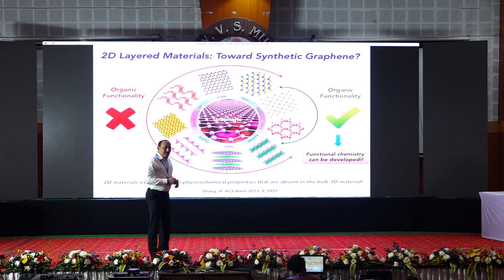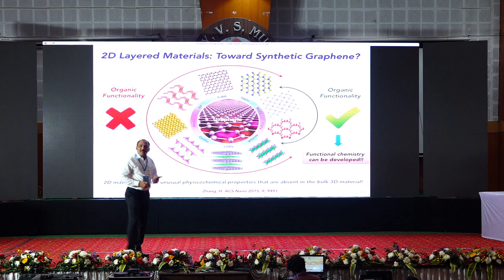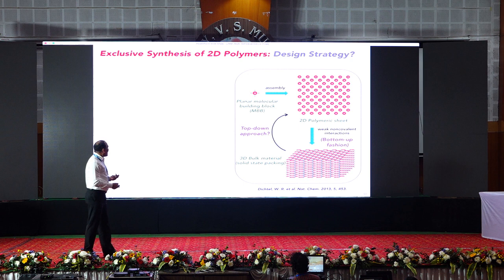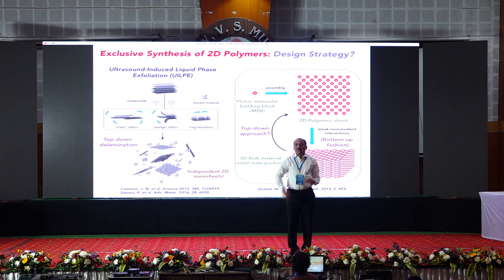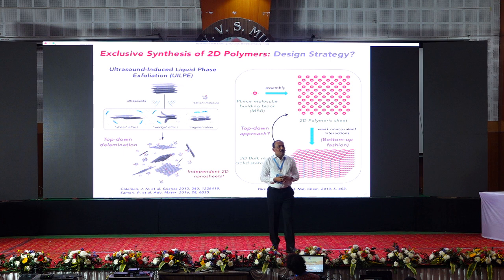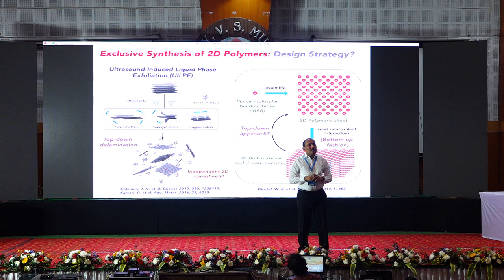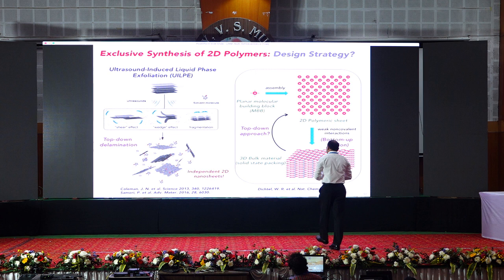How do you develop 2D organic nanosheets or metal organic nanosheets, for example? Can we do this? What has come to be known in the literature is that if you have a layered material, put this layered material into an organic solvent and do an ultrasonication, the solvent molecules sneak in between the layers and the layers can be separated out, and the layers now get stabilized with the solvent molecules, and there is a mechanism. Ultrasonication is a way, provided you have a layered material. But how do you get to the layered material in a way that you want from organic molecules? It's not easy. But then if you can, that's where the joy is.